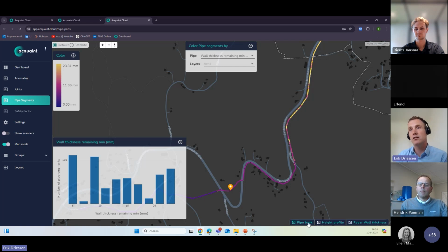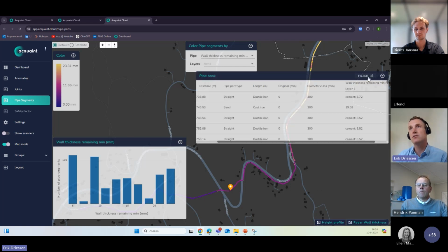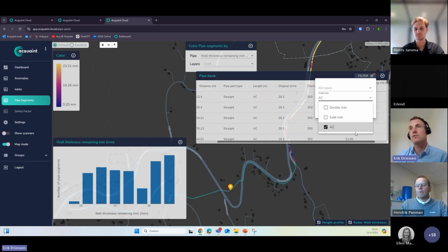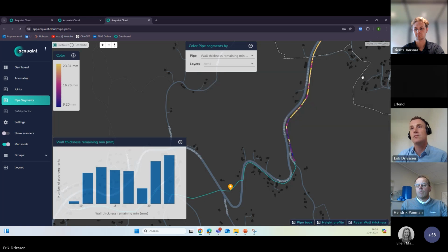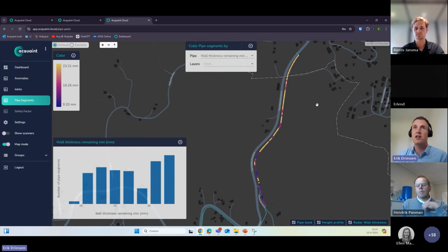So what I open the pipe book here, I select the filter, and I focus at the asbestos cement first. So this is the asbestos cement pipeline. We have selected the minimum wall thickness, and this is a scale from 9 up to 23 millimeter. And maybe you remember from Riens that the original wall thickness was 28 millimeters.